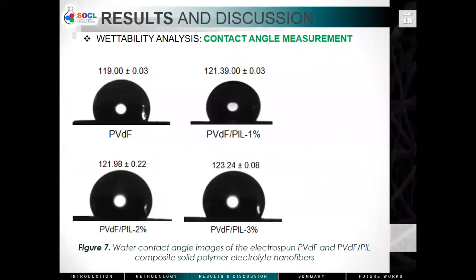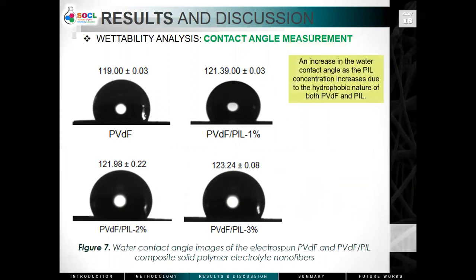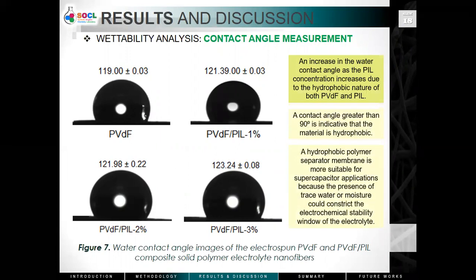The wettability of the electrospun nanofibers was studied using the sessile drop method. The generated contact angle images presented an increase in the water contact angle as the PIL concentration increases. This is due to the hydrophobic nature of both the PVDF and PIL. A hydrophobic polymer separator membrane is more suitable for supercapacitor applications because the presence of trace water or moisture could constrict the electrochemical stability window of the electrolyte, hence suppressing the energy density of the device.